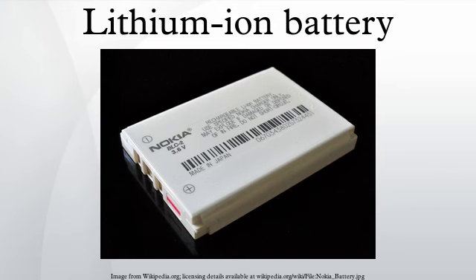A 2004 study found that for most cycling conditions self-discharge was primarily time-dependent. However, after several months of stand on open circuit or float charge, state of charge-dependent losses became significant. The self-discharge rate did not increase monotonically with state of charge, but dropped somewhat at intermediate states of charge. Self-discharge rates may increase as batteries age.